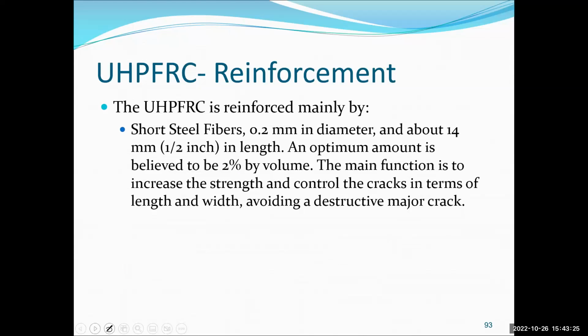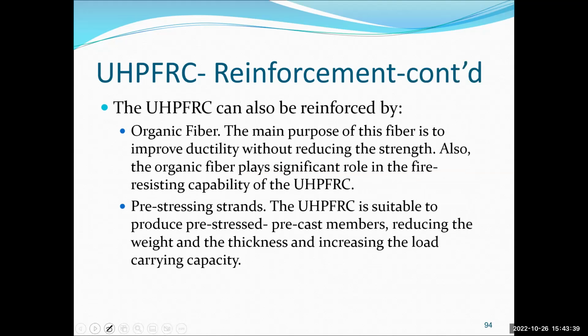Now, for the ultra high performance fiber reinforced concrete, the fibers would be steel fibers with a diameter of 0.2 and a length of approximately half an inch. By volume, not too much, about 2% by volume. Now, not only that, we have organic fiber. In this case, the main purpose of the organic fiber is to improve ductility without reducing the strength. Give some ductility, because it lets it deflect.